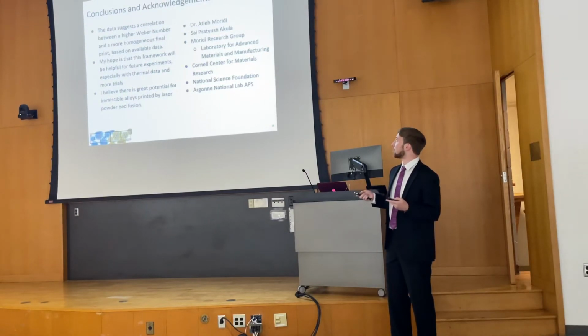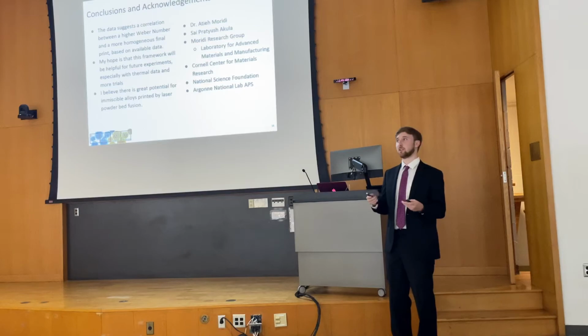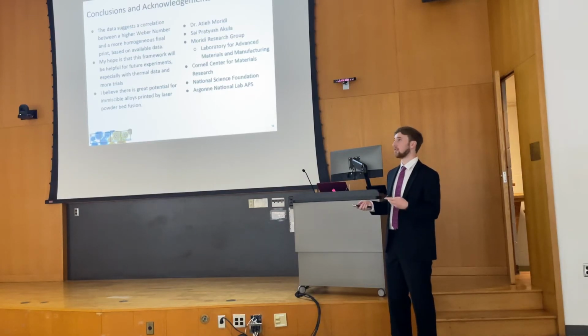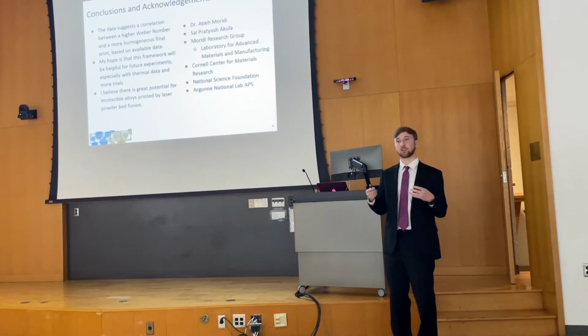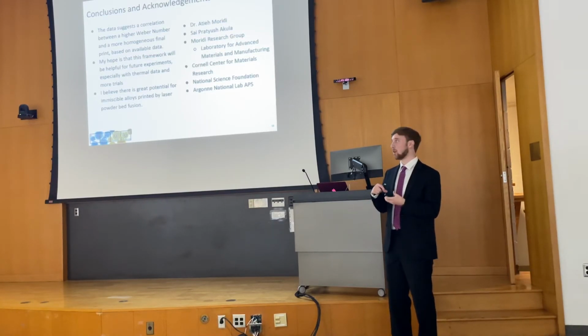So the data suggests a correlation between a higher Weber number and a more homogeneous final print based on the available data that we have. More trials will certainly be necessary to develop an actionable conclusion on this, and also for more material systems and a larger range of printing parameters. My hope is that this framework will be helpful for future experiments, although those will most likely need to include thermal data so that we understand the temperature gradient within the melt pool over time, because there is great potential for immiscible alloys.